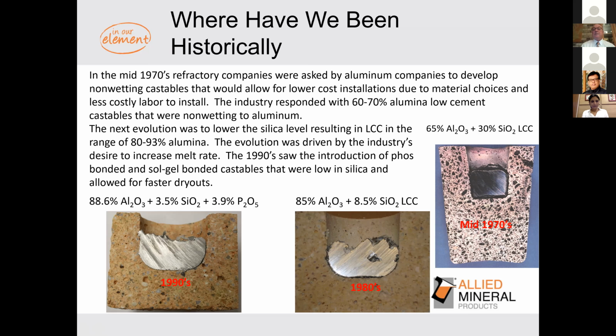So for many years, again, it was in the 70s, there was again the 65% alumina. Even though it had 30% silica, the non-wetting agents are very powerful for minimizing the reduction of silica. Again, in the 80s, they would already be using an 85% alumina brick. So we developed an 85% alumina monolithic, again, trying to minimize the silica content from 30% down to 8.5%.